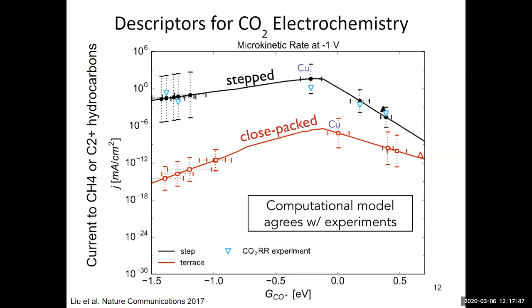and those are all the materials that just make a bunch of hydrogen. And so copper is sort of in this privileged space where it has a very small and slightly negative CO binding energy. And so this is what I would consider a necessary but not sufficient condition at this point for finding a new material. If I find other materials in here that have this property, I don't think all of them are going to be experimentally awesome, but I can tell you that the ones out here and the ones out here are probably not going to be interesting, and we shouldn't be spending experimental time testing those.